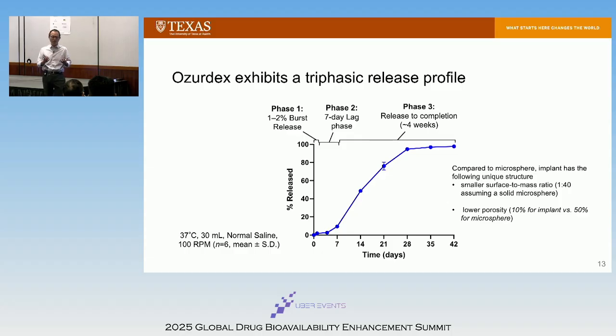So dexamethasone has a very interesting PK/PD correlation. That's actually another layer of complexity. But apparently, we found out later, for dexamethasone to be effective, you actually need a very, very low level of dexamethasone concentration. What we see here, this burst, if somebody can develop a dexamethasone implant that just releases, like, the first 7 days at a very low release rate, that would be perfectly effective. Actually, the later release burst creates side effects, creates high ocular pressure, okay?